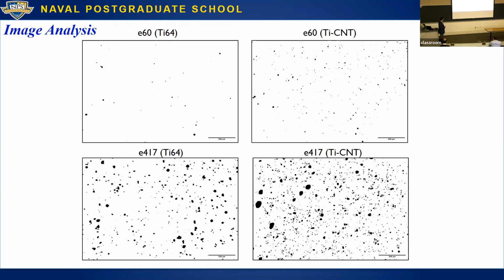And then this is the porosity that you get. There's different sources of porosity. If you have very spherical porosity, a lot of that actually just comes from the starting powder. Especially when we mill it, we can get entrapped air. And that's not terribly problematic. It's also very closed, so it doesn't form an interconnected channel. At higher energy density, not only do we get more porosity, but a lot of porosity starts becoming asymmetrical. And that's because some of it is actually due to evaporation occurring, because the melt pool is very unstable. You have a very high temperature, and then you also have splashing. You actually have a melt pool that's so turbulent that you get splashing, and that can cause inclusions, and that's some of the source of porosity.